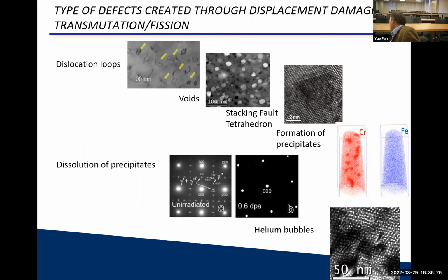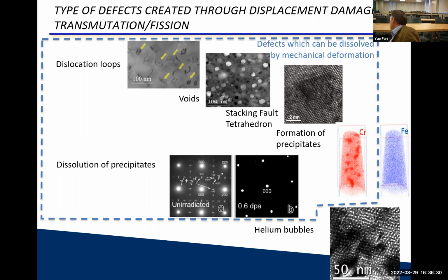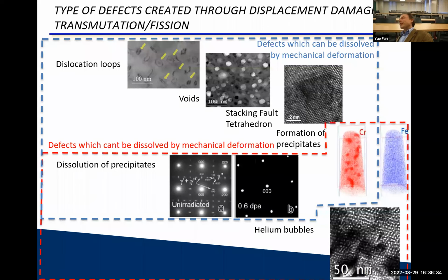And helium bubbles. And for the remainder of this talk, I would like to separate it into defects that may be dissolved by mechanical deformation and defects that usually won't be dissolved by mechanical deformation. So stacking fault tetrahedra, if a dislocation loop is there and a dislocation comes, they can be absorbed by those. And that leads to different mechanical performance than, for example, helium bubbles, which may change their structure, but they won't actually get dissolved.